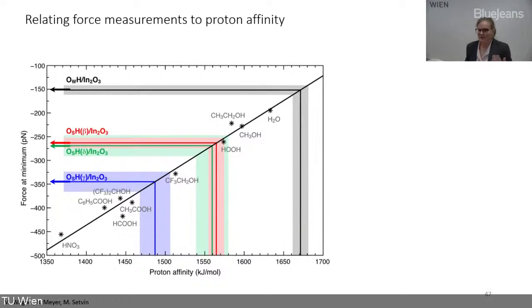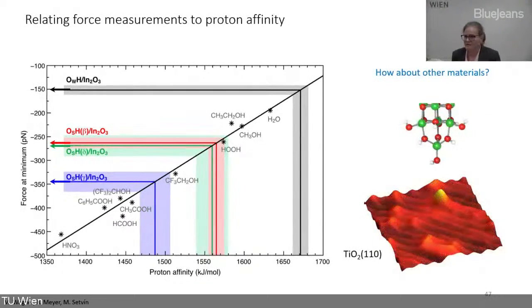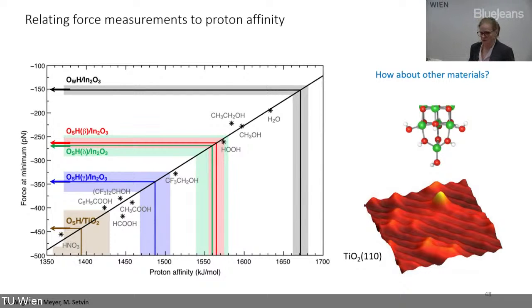And to top it off, we've been able to do that not just for one specific surface, but we used the same type of tip on another oxide surface, the TiO2(110) surface, and got the proton affinity that way. I don't want to go into more detail, but what I wanted to convey is that we found a novel way to evaluate surface hydroxyls one by one at regular sites, which also opens the opportunity to look at steps, defects, dopants, and so forth, even on insulating materials. The new ERC grant I've been granted will look exactly into this, trying to make this into an actual measurement.